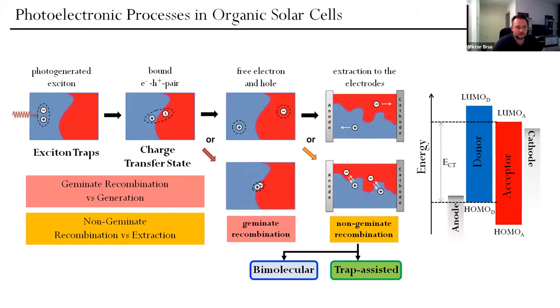electrons should move through the acceptor network, and holes should move through the donor network. And if these networks are too small and these conductive channels are too narrow, they will be lost on the way to electrodes. So there should be some sweet spot in the middle. And it's a big field of study trying to optimize the morphology of organic solar cells, and that's very important.